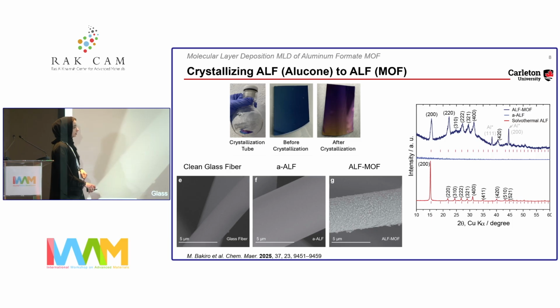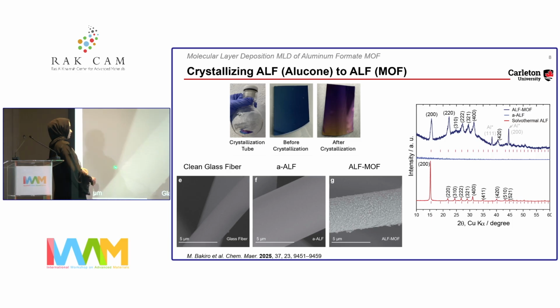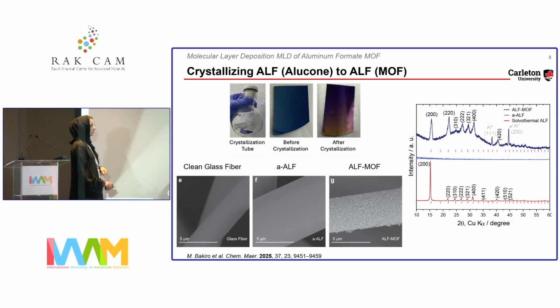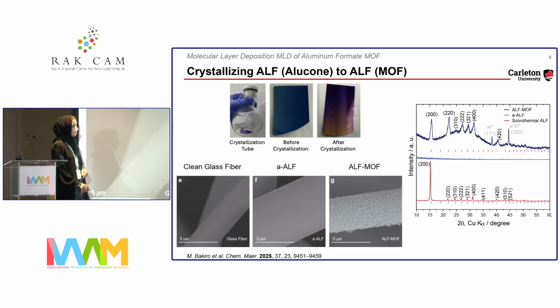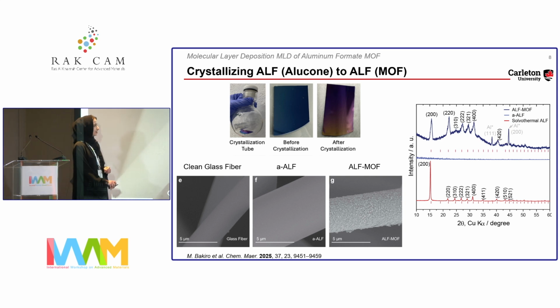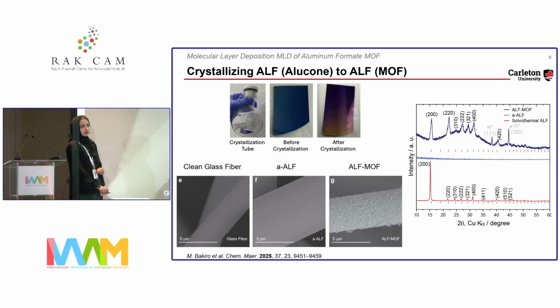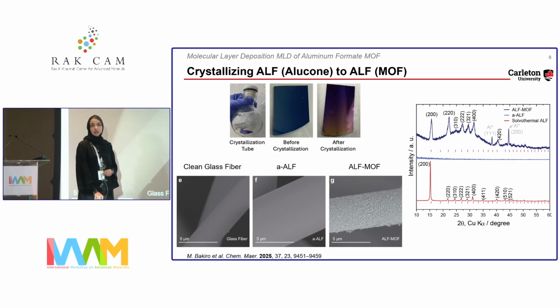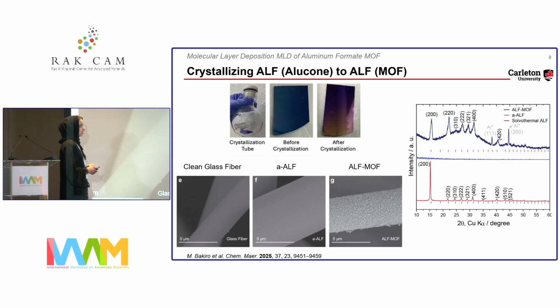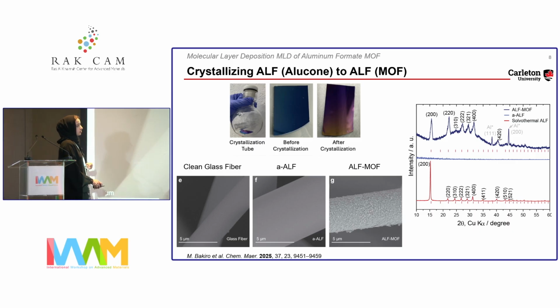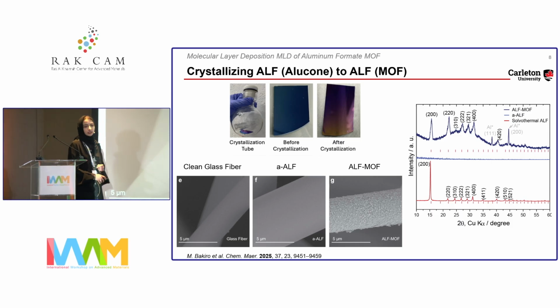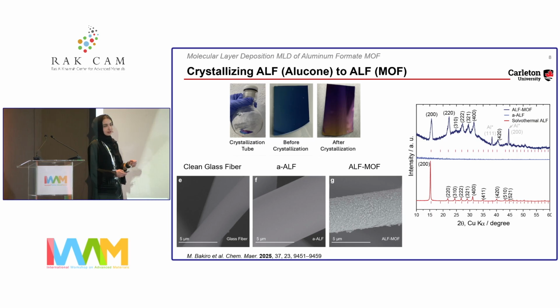However, if you look at it by SEM, this is the glass fiber without depositing anything on it. This is the as-deposited thin film. You've got to trust me, there's something here. It's just super conformal. And then here is after it got crystallized. And look at these beautiful crystals on the surface. And it's very conformal, like it's taking the shape of the glass fiber. The XRD compared to the bulk is very comparable. Those extra aluminum peaks are coming from the holder on which we did the analysis. So we crystallized it. Yay.